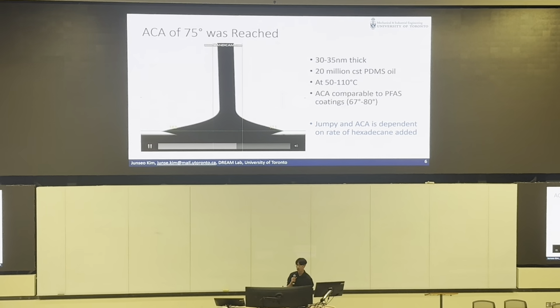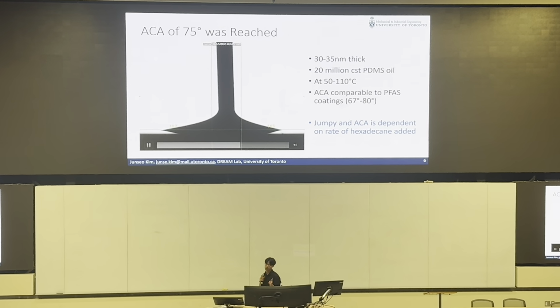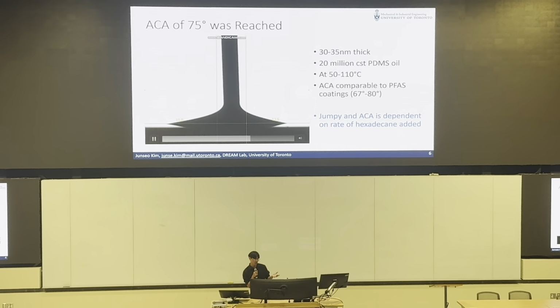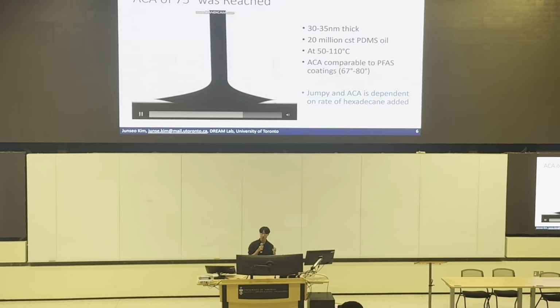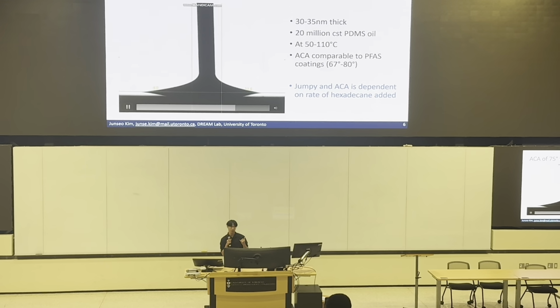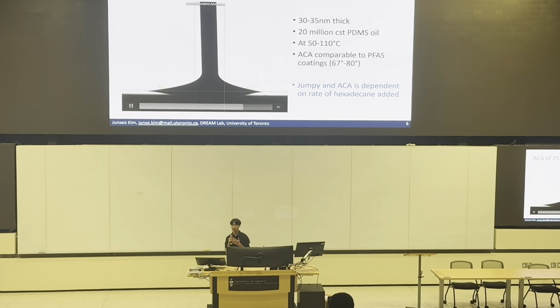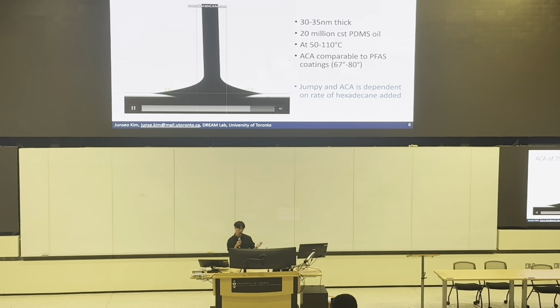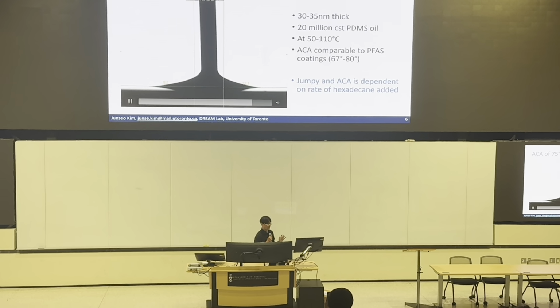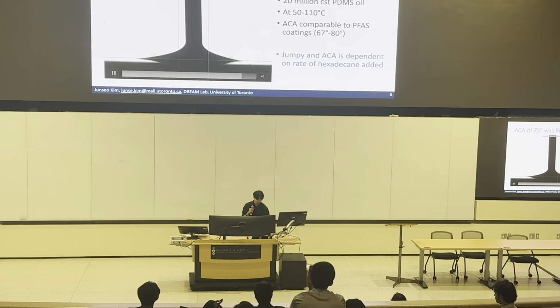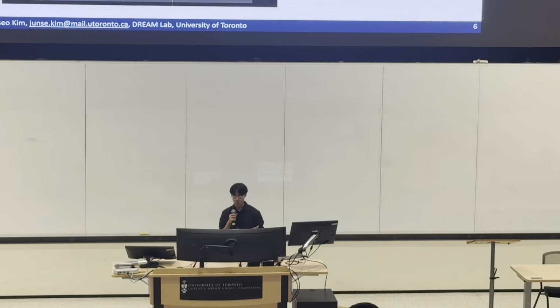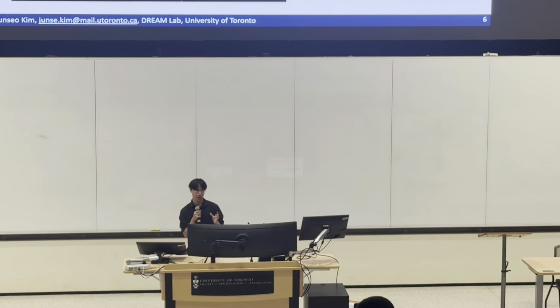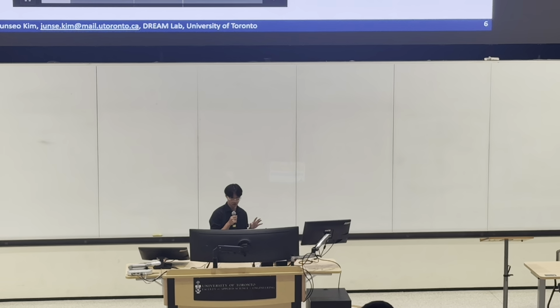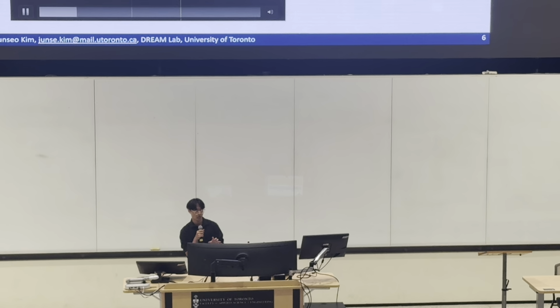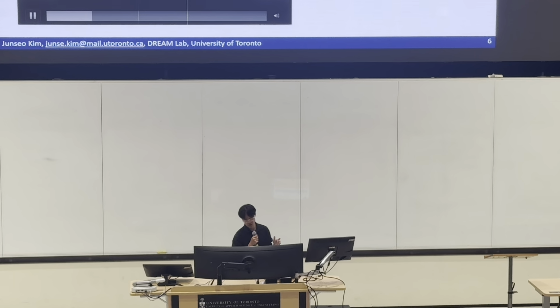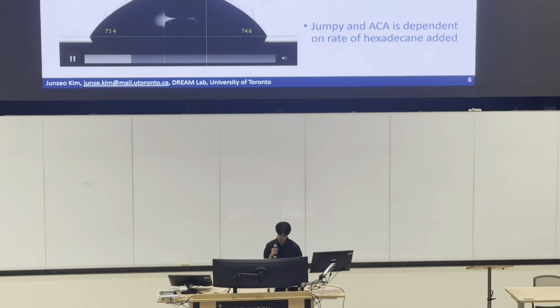The reason this is interesting and exciting is because the advancing contact angle, which you said is a quantifiable measure of oil repellency, is comparable to that of PFAS, which is something that we're trying to move away from because it's toxic. However, there are some downsides. If you can see from the video, when I'm advancing the liquid, you can see it drops quite a bit, which decreases the credibility of some of the measures that I have and increases the error. But aside from that, it's still pretty exciting.